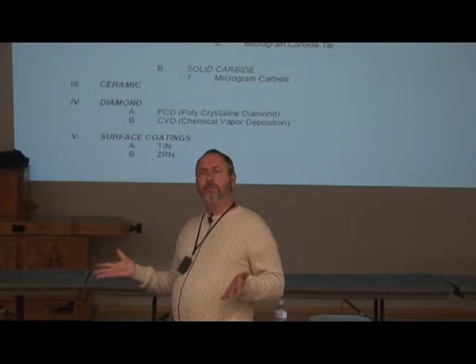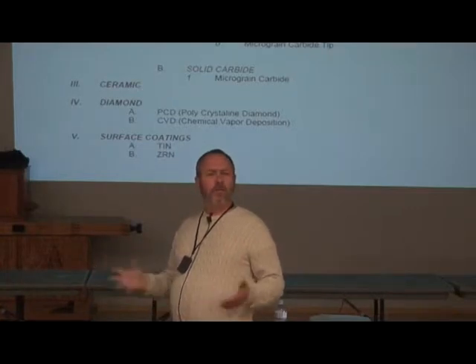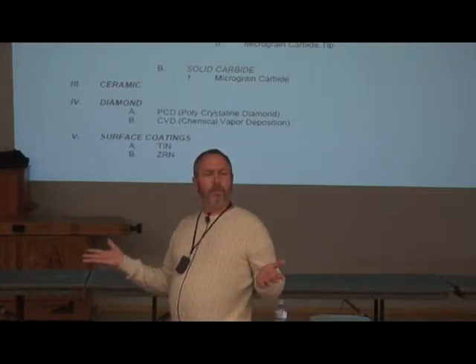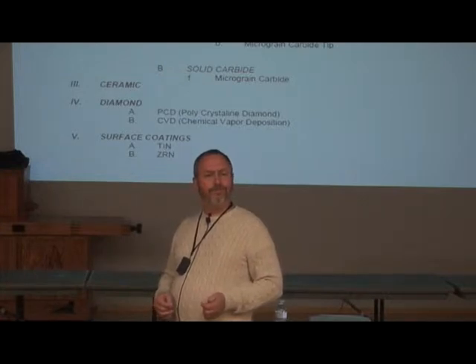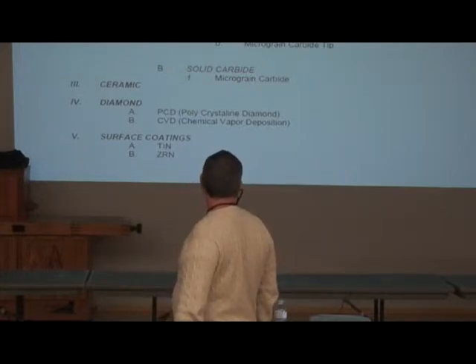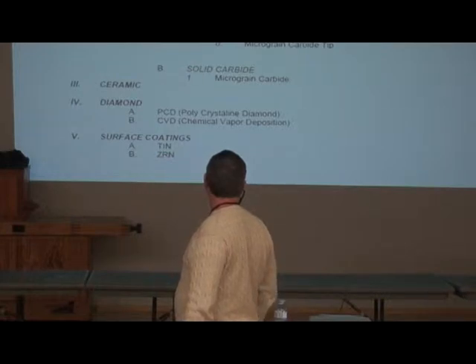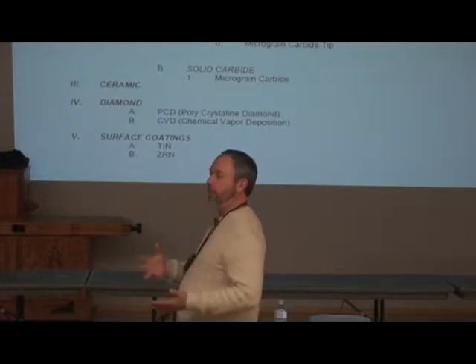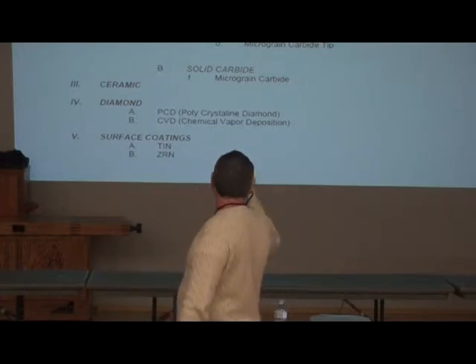That is a trade name for LaSalle steel. It's an 1144, resulfurized medium carbon steel. 4140 is a very good heat-treatable material. And then your best is the H13. Then they braze the carbide tip to that piece of metal that holds it. And then you have silver braze and you have a nice little tip.